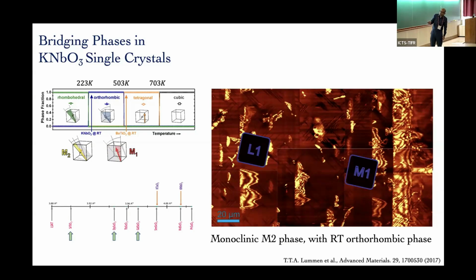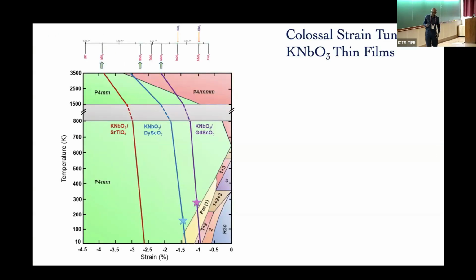So this is going to have to fit to the template. So it's going to have to shrink. So when it shrinks, it's under compression, right? So all of these 3 films are going to be under compression, biaxial compression. And I'll show you what happens. This is the phase diagram for temperature versus strain. This is all compressive strain, done by Longqing Chen, who is an expert in phase field modeling. He is my colleague and probably the foremost expert on phase field modeling in the world. He has a very bright student, Aidan Ross, who calculated this.